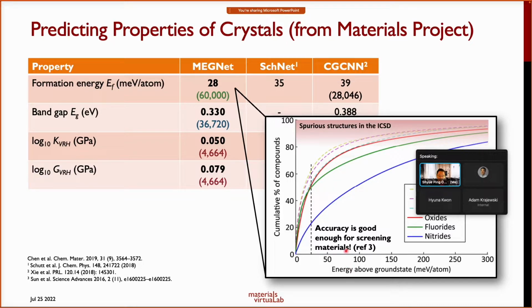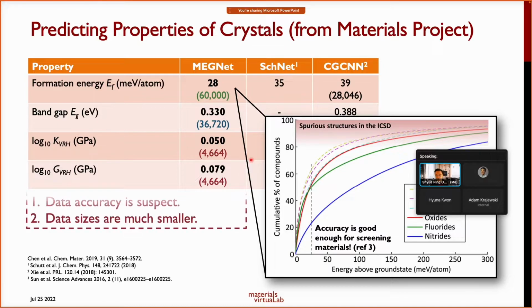And what this work found was that basically about 80% of the materials in the ICSD fall within a range of 70 to 100 meV from the convex hull, right? And this accuracy of 28 meV per atom is well within that 70 to 100 meV per atom. And so it is good enough for you to make determinations of the stability, right?